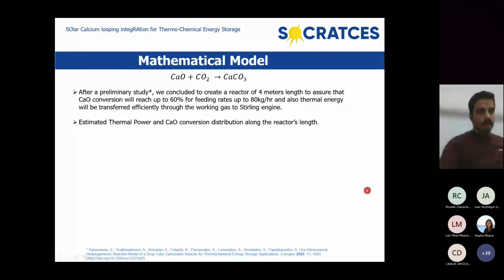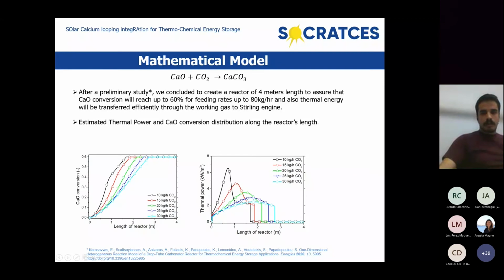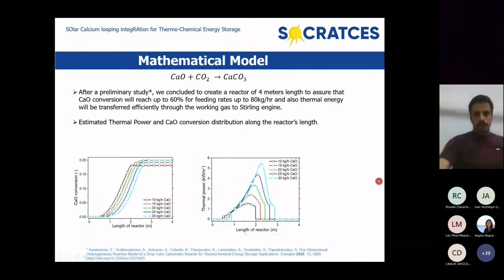Now, after evaluating those results, we concluded that the 4-meter reactor was enough to assure the desired calcium oxide conversion for feeding rates up to 80 kilograms per hour. And here you can see the alteration of the estimated thermal power and the calcium oxide conversion distributions along the reactor's length, and the dependence in the variation of carbon dioxide flows, calcium oxide flows, pressure, and wall temperature.